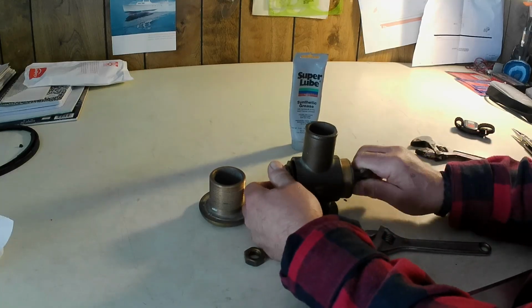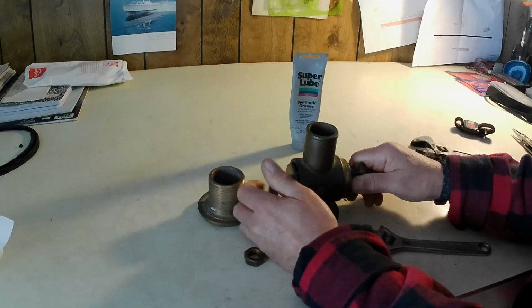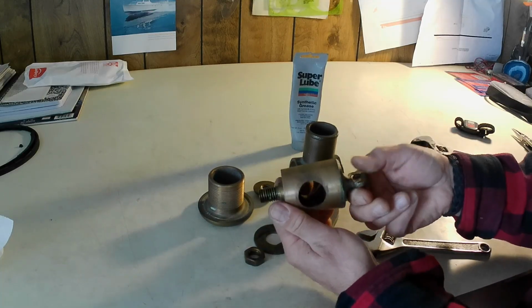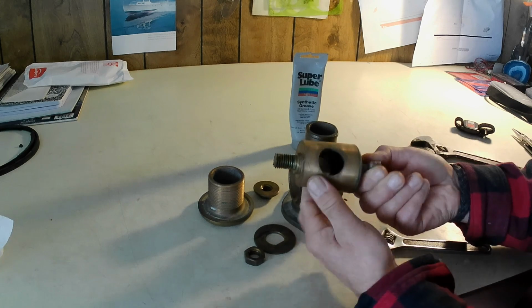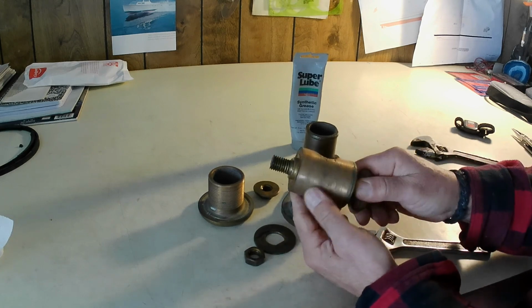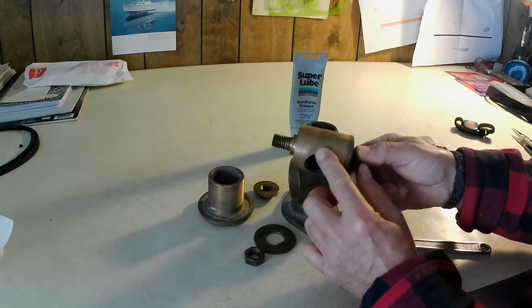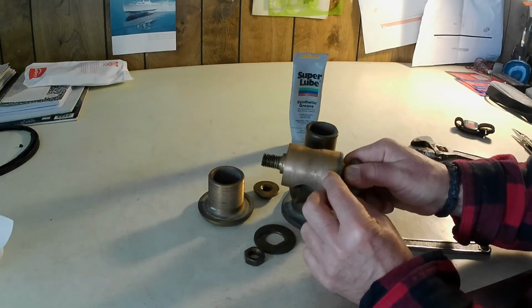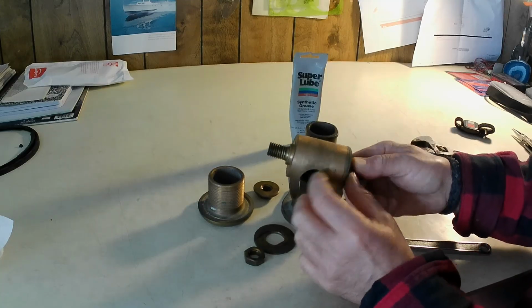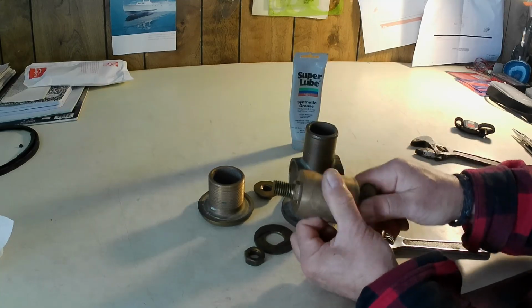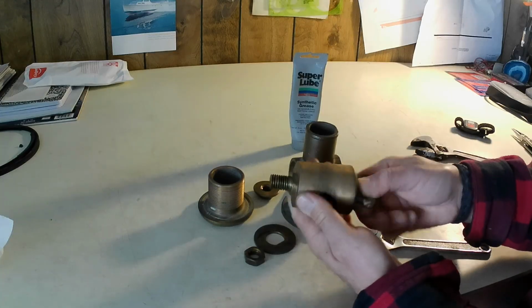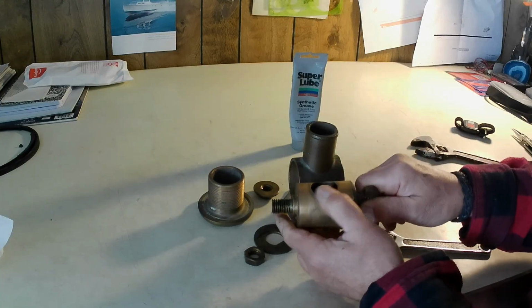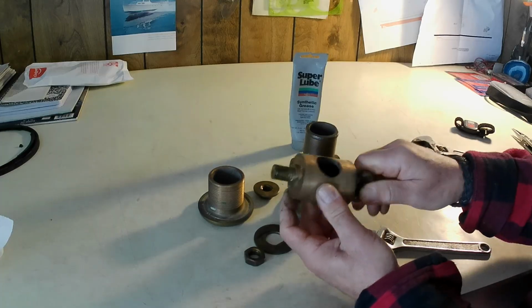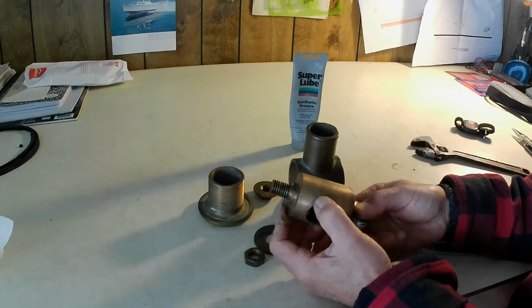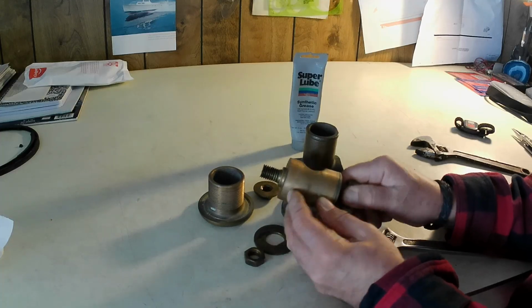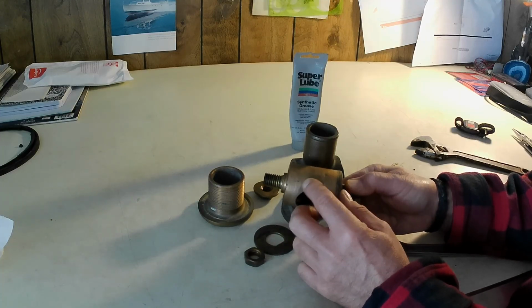In that process, though, what you're really doing more than anything is you're pulling it apart and you're observing this barrel. You can see that this has been left in the closed position for quite a while just based on this darker ring, but there's no corrosion here. In fact, you could lightly clean this up with some emery cloth if you felt like it was starting to get grooved. What you will see as these age is sort of a pink color, a pitting of the surface.